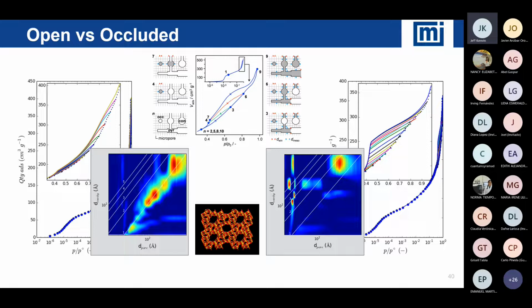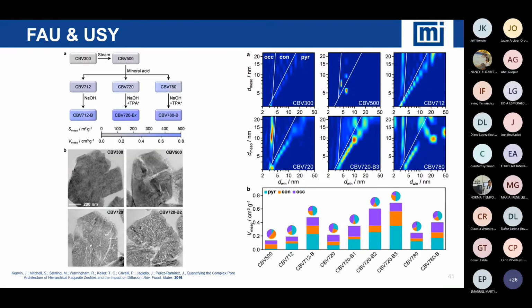So by using these techniques of using multiple isotherms and this scanning technique where we partially fill the pore structure and then empty it and calculate pore size distributions for all of these different hysteresis loops, we're starting to gain some insight with respect to the connectivity in the pore. So do I have a small window connecting to a large pore, or do I have the window and the pore being approximately the same size?